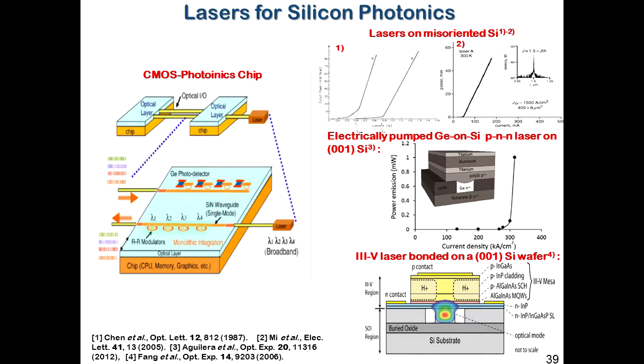They want absolute 001. That's their preference, and that's how it's going to be forever. Then, this laser was demonstrated by Kimerling at MIT, germanium on silicon, a tensile strained germanium, and doping it to degeneracy, and they get a threshold current density of about 300 kiloamps. And then that laser is going to melt before it can do anything useful. And then you have this technology from Santa Barbara, that they bond a high performance, let's say, 3-5 based laser onto the silicon wafer, and you can have the guiding either in the silicon by leaking the mode, or in the 3-5. That's a variation. The problem is the bonding technology and the long-term reliability of it. So that's the status.